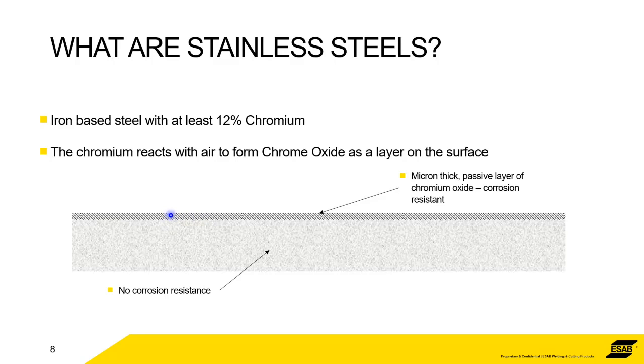The problem is when the chromium oxide layer is removed and there's no oxygen for whatever reason. If it's submerged in some kind of liquid, if there's no oxygen, then you can't get the chromium oxide, so you don't get the corrosion resistance. It's the chromium oxide that causes the corrosion resistance.